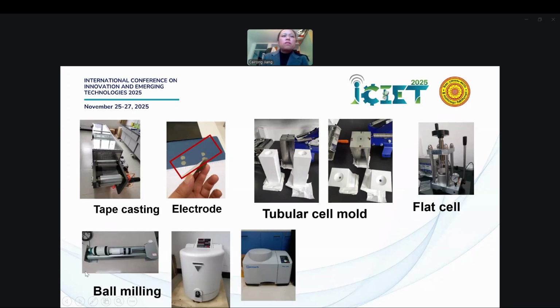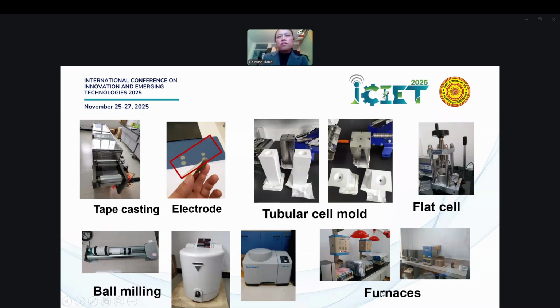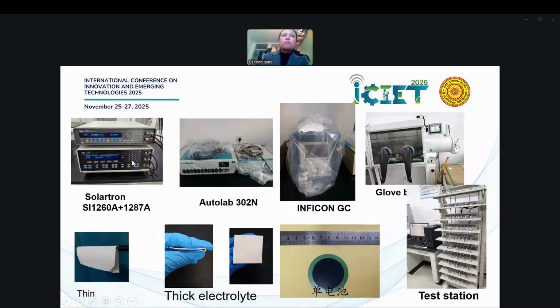And this is another machine for preparing slurry to make thin films, because in cells we usually need a good cell, meaning with low resistance, and the thin ones shown here are good for fuel cells. And there are some other furnaces for sintering or calcination. We have some test machines like Solartron, two machines combined to get the resistance test and the current density test, and some other bigger ones that can reach higher current density values, and some gas tests if we are interested in the gases from the outlet.